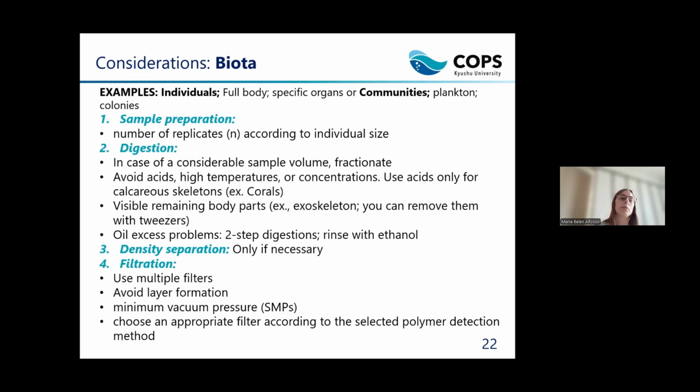Also remember to avoid the use of acids and high temperatures or concentrations. Use acids only for calcareous skeletons, for example, calcareous content. If you need to eliminate the calcareous content, you need to use acid. You cannot avoid it, but always use a precautionary approach using low temperatures and low concentrations.